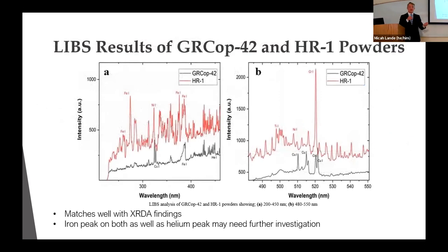And the same thing can be said taking these over to get LIBS performed on them, where they all fall exactly in the range that we would expect them to be. Again, just vetting our X-ray diffraction, our XRF, and different methods to make sure this powder is chemically what we want it to be. There isn't too much of note here, but what is interesting is we have a fairly significant iron peak on both, which could be due to some sort of contamination. That's something we need to look into in the future.